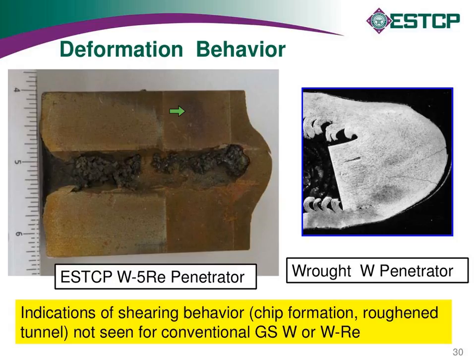Again, here's the section target from that shot with the glycine nitrate processed tungsten rhenium. First thing you notice is the penetration tunnel is roughened. You can see the roughened walls of the penetration tunnel, and there's lots of little chips of the material lining the tunnel. If you make a tungsten rhenium alloy in the conventional way with conventional grain sizes, you get a different behavior. We haven't shot tungsten 5% rhenium, but people have shot tungsten 26% rhenium and 10% rhenium, and they all behave basically like pure tungsten. Extremely stable mushrooming behavior. You end up with a very smooth penetration tunnel, not the roughness that you're seeing on the walls, and it never really lets go of the material.